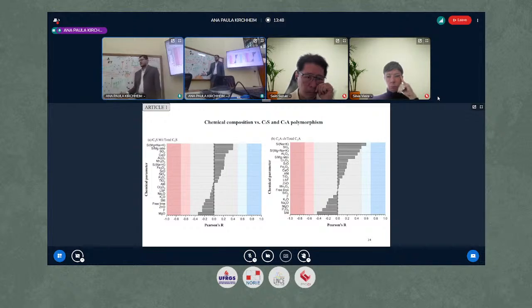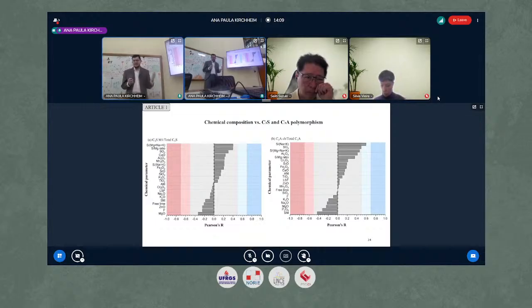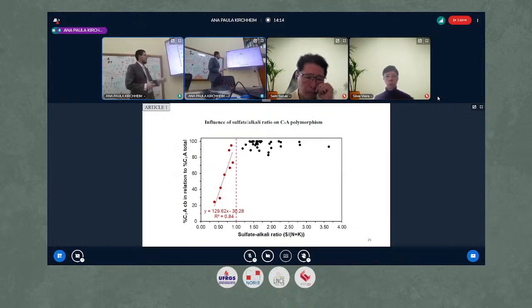Here we see the polymorphism, and the polymorphism of C3S was, according to the literature, that increasing sulfate stabilizes C3S in M1, while increasing magnesium stabilizes C3S in M3. And regarding the C3A polymorphism, the main influence was the sulfate alkali ratio. We see clearly from this graphic, above 1 sulfate alkali ratio, we almost only have cubic C3A.